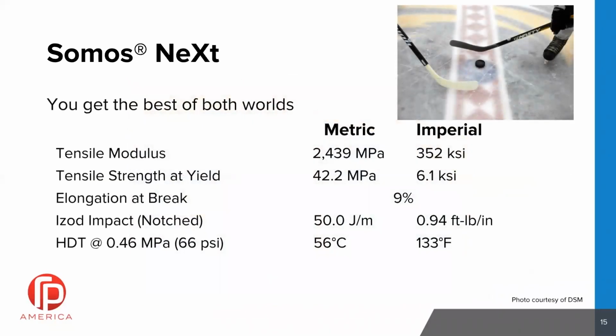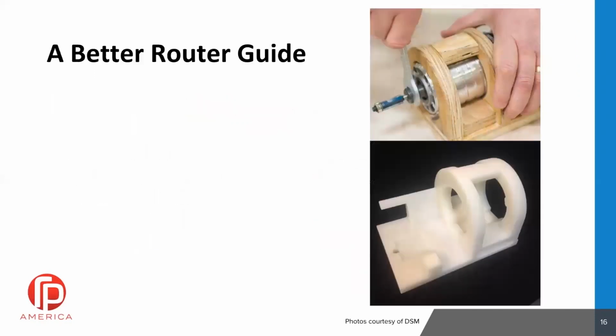And so we're getting the best of both worlds here. We have good tensile modulus, we have really good strength at yield. The elongation is a little less, but the temperatures are getting higher. So the impact resistance is also really good on this as well. That image there with the hockey sticks, those are actually 3D printed blades, and you can use them to play hockey. They're that tough, and they will hold up.